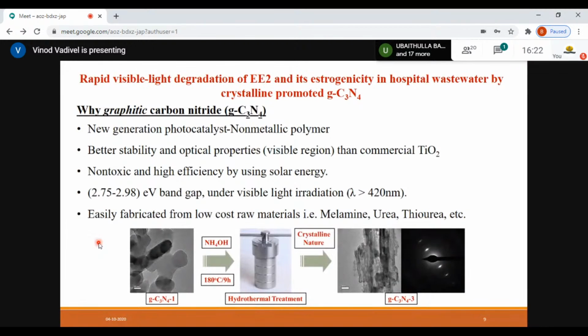Then we understood we needed to find another visible photocatalyst which can work for EE2 removal. And then we found graphitic carbon nitride, which is again a new generation photocatalyst, a non-metallic polymer. We found this system is very cost effective. It's comparable to titanium dioxide, which is commercially used as a photocatalyst mainly. So it's really environmentally friendly, visible region active, and you can modify its band gap, which closely resembles our solar photocatalysis band gap range. And the materials can be easily prepared from simple cost-effective materials like melamine, urea, thiourea, etc. So all you need is the system to have carbon nitride.